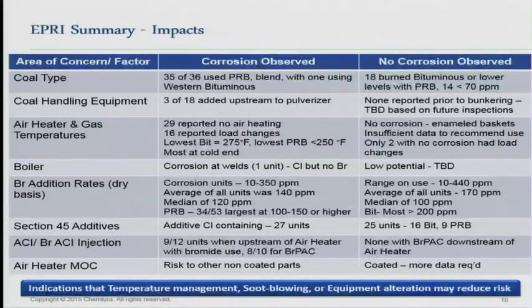When you look at the corrosion, where there was corrosion and they were burning PRB, 34 of the 53, the largest additions were 100 to 150, but where they didn't see corrosion, it was even higher. So again, there are lots of things here showing interesting trends, nothing that's a smoking gun, but for the most part, very interesting trends on what you can look at and how you need to operate.